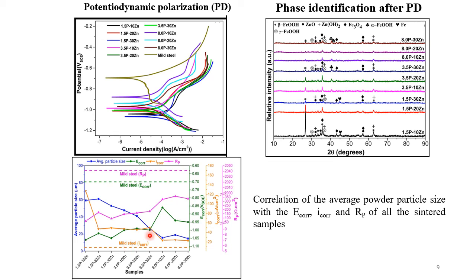And we have shown here that with the decrease in the particle size, the Ecorr value increases, that is, the 1.5% hybrid sample, which has a much larger particle size, has a more negative Ecorr and a higher corrosion rate value as compared to the other sintered samples.